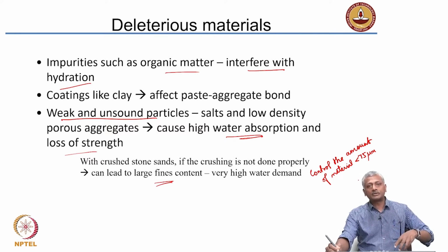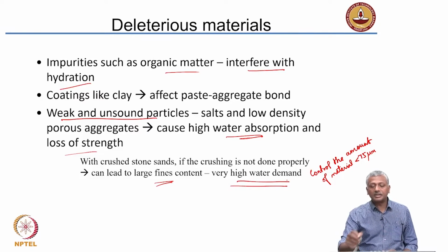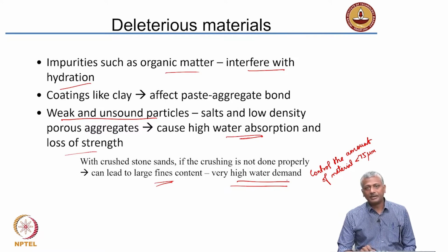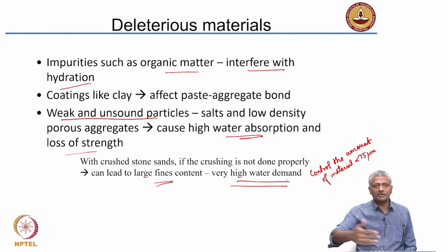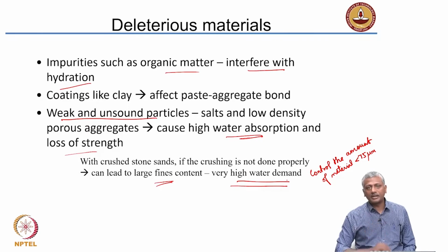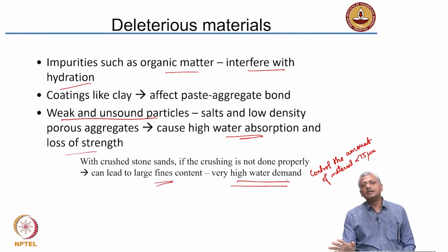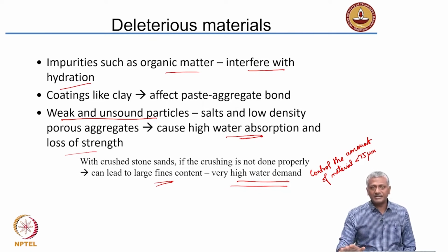What will happen if that comes into your concrete from the sand, it will start increasing your water demand tremendously, and you will get a lot of problems in controlling the quality of your concrete. Okay. So, that is one thing you need to be worried about when you start using crushed stone sand. Okay. In river sand, typically you do not get that, because the action of the river nicely washes off the very fine particles, and you get a good quality aggregate. However, apart from that one problem, in most cases crushed stone sands can produce concrete of as good quality as river sand. Okay. Crushed stone sand and river sand will produce concrete quality which is nearly similar, except for this one problem that you may get more fines in the sand when you have crushed stone sources. Make sure that these fines are in the limit that is prescribed by IS 383.